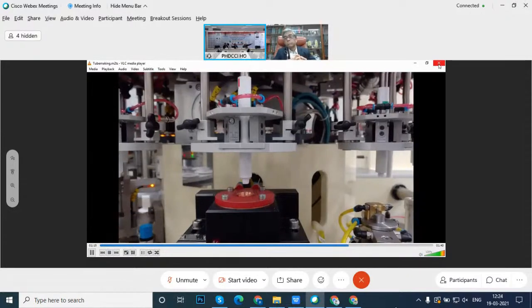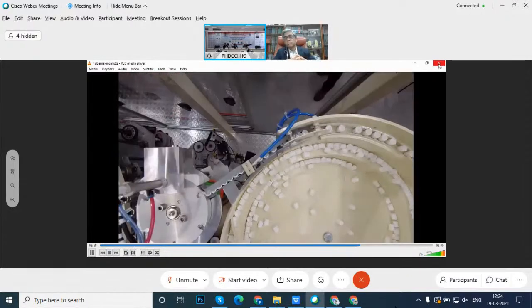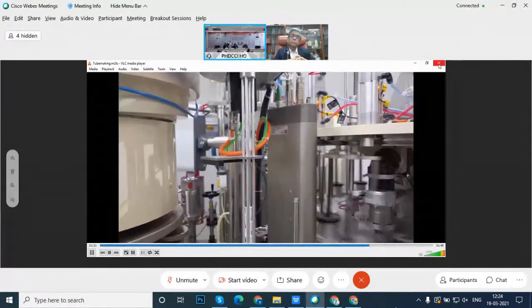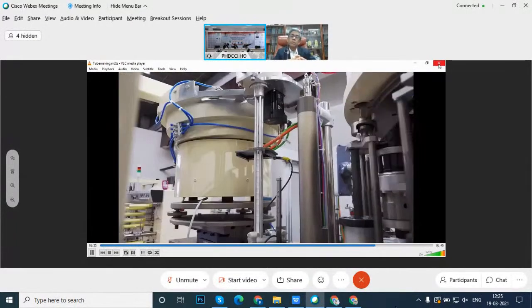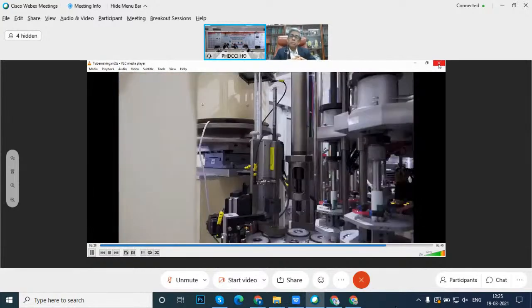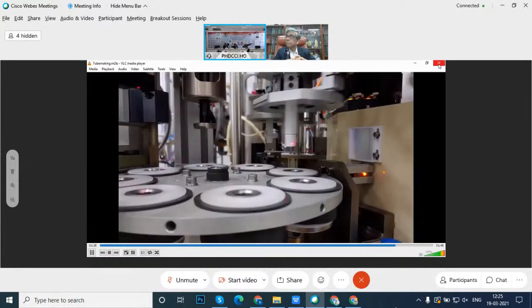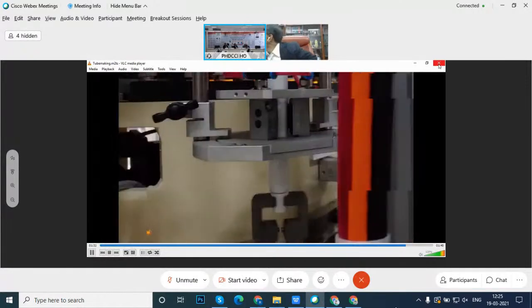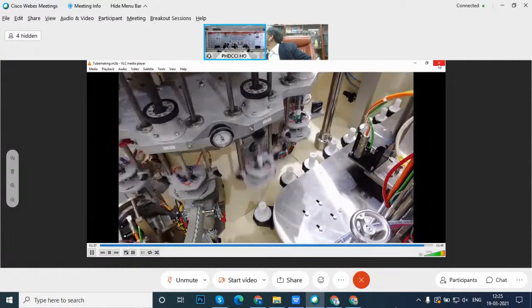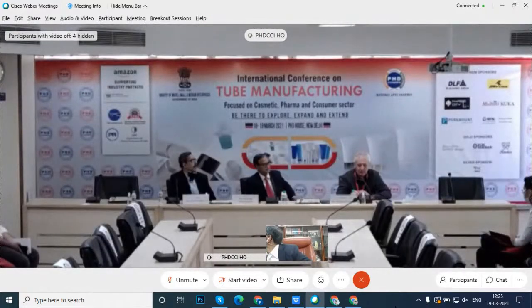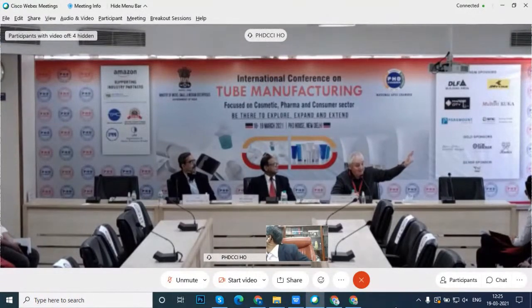We wash shoulders before washing the body, then wash the body, then we do sealing of the shoulders, and then it looks like caps are coming. In this case, those are conical caps, simple caps. On this table, we also can do orientation of the cap in case there is anything on the cap. And this is the capping, and then this is transferring to the feeding process. Feeding machine is controlled with the feeding process. But the feeding machine, as I said, is not very different from a standard feeder. Most important is really this moment of transfer.